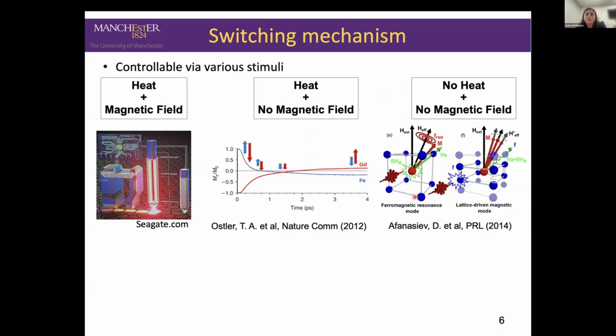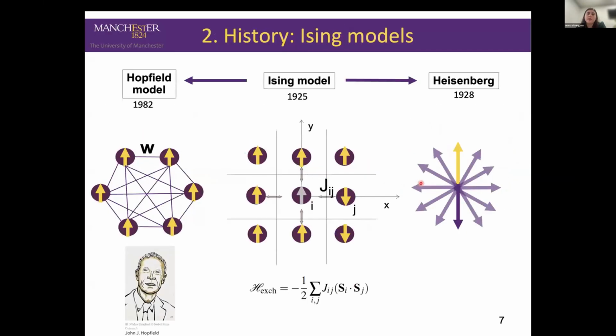And also it has been proposed a mechanism of switching the magnetization or controlling magnetization by coupling your laser pulse excitation to the phonons, to the lattice vibrations, which will modify the local properties of your magnetic system and hence the anisotropy, and can drive precession and hopefully switching. And this type of phenomenon is assumed to employ less energy. So it's a more energy-friendly way to write your information.